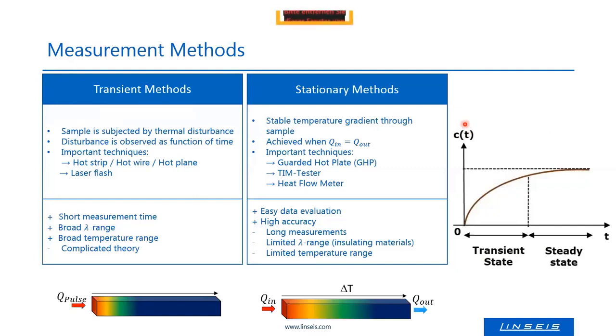When the thermal conductivity needs to be measured, in principle, there are two different methods. The older one is the stationary methods. For many, many years, thermal conductivity was measured with plate instruments, which you might know. The working principle is that you have a sample, a hotter plate on one side and a colder plate on the other, and you wait until you have a constant temperature gradient within the sample. The heat flux is measured, and from the heat flux and the delta T, the thermal conductivity can be easily calculated.